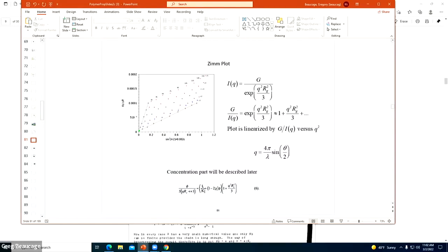That's the osmotic compressibility. And then the other part is Guinier's law. Like 1 over Guinier's law gives you this 1 plus, like the Ornstein-Zernike thing upside down. Right? So that's called the Zimm equation. It's for low Q, for low Q RG, and then it's got this osmotic compressibility term. So you can determine at 0 concentration, you can get the molecular weight. From the dependence on concentration, you can get chi.